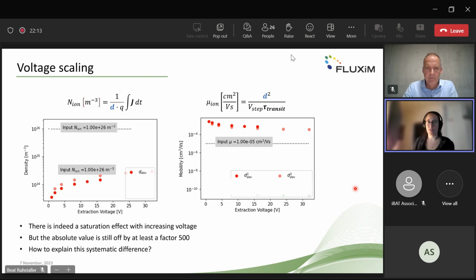this is now the beauty of this synthetic data. We now know what we put inside, and you can already see that it's quite far away from each other, so almost 2 orders of magnitude depending on the extraction voltage. And also the mobility, which we would get from the transition point or the transit time. If we use the thickness of the device, we are quite off of the real value. And so the question was a bit, how do we explain that?